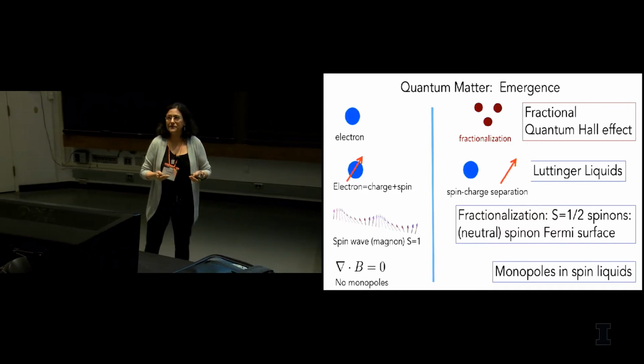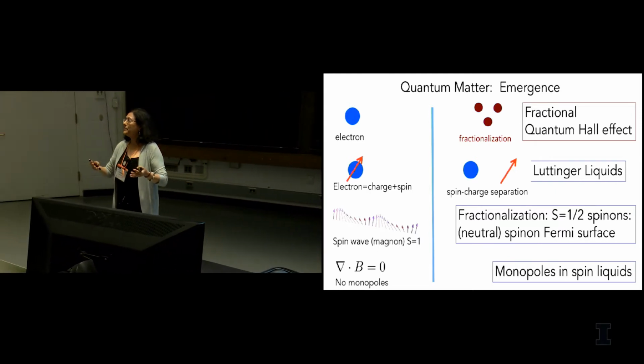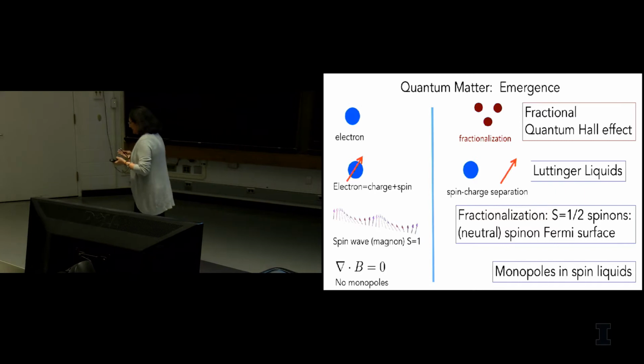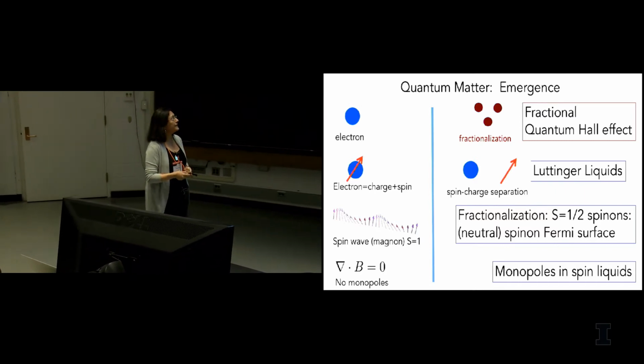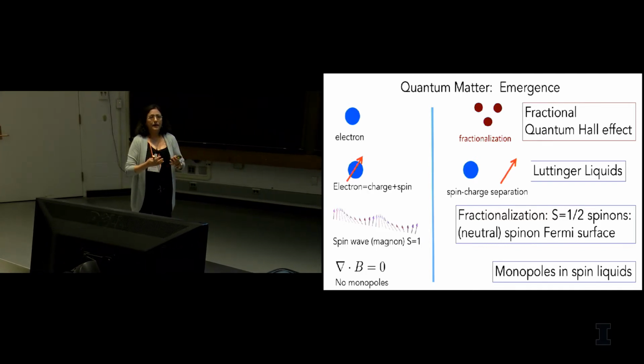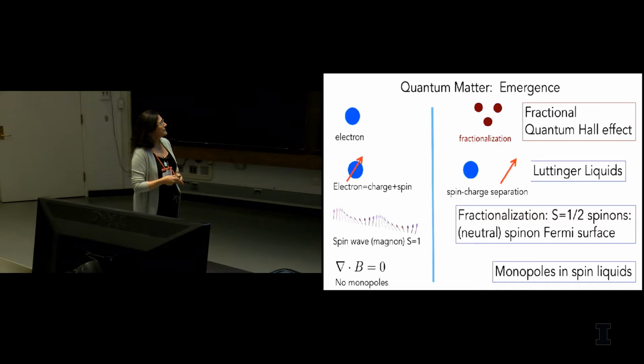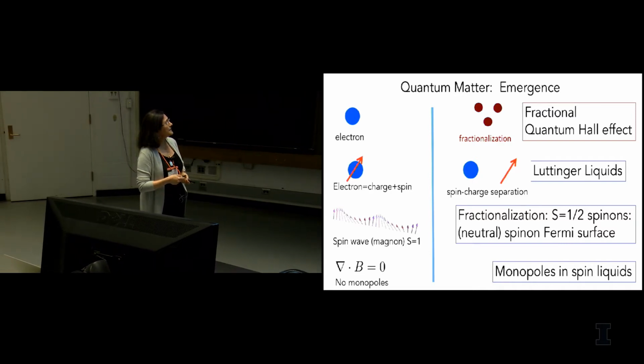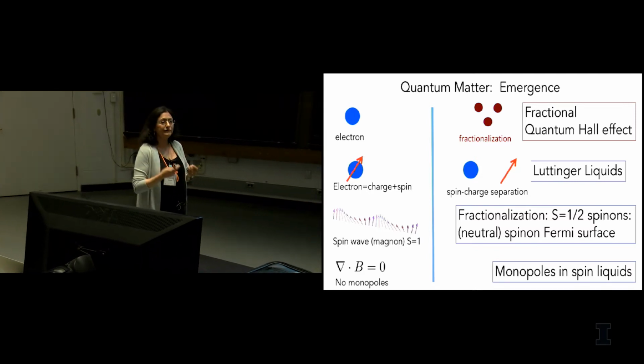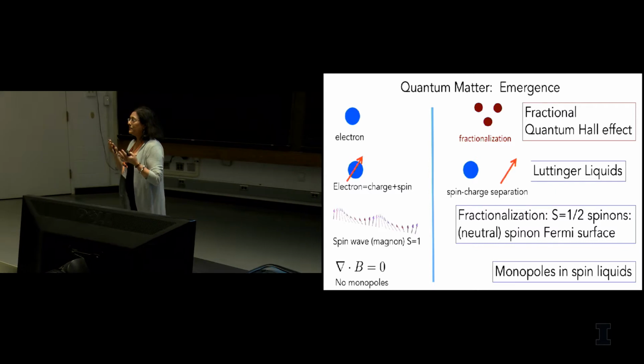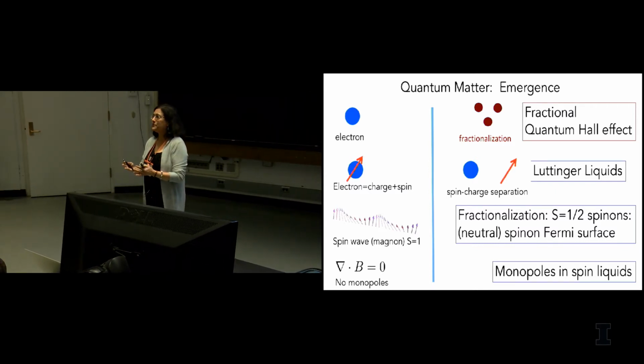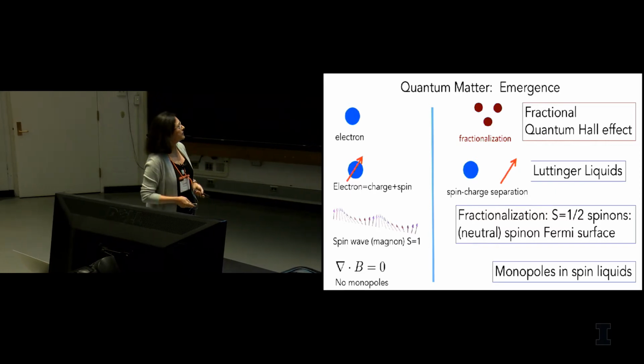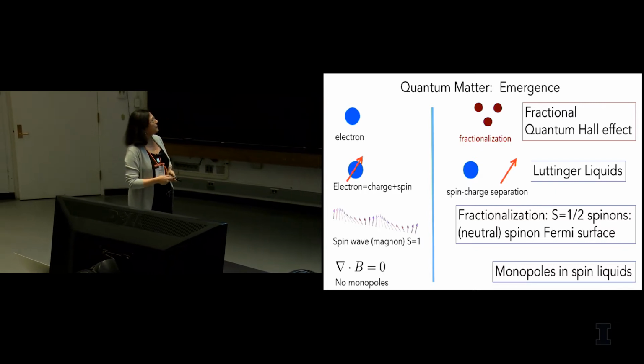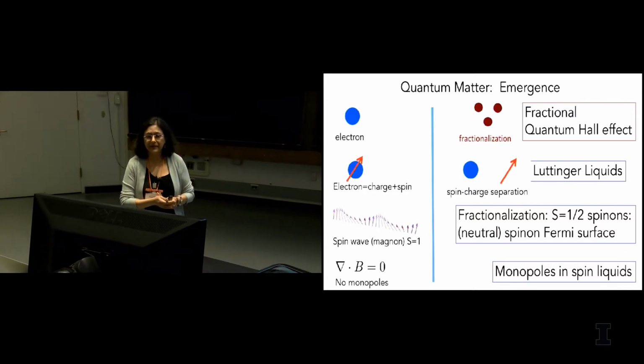And these are not just figments of someone's imagination. Theorists have been proposing these, but it's been just amazing to see how experiments have verified this, for example, seeing a linear specific heat and thermal conductivity that is proportional to temperature, very much the behavior that Fermi liquids or something with a Fermi surface would give, but in an insulator, which has no Fermi surface. It's these emergent spin-half spinons, which are fermions, making such a Fermi surface. And these have been observed. And, seeing monopoles in quantum spin liquids and so on.